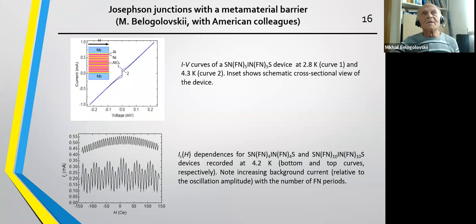But in several tens of these junctions, with aluminum oxide and without aluminum oxide, a Fraunhofer pattern was not observed. Rather, we saw a periodic structure, which is typical for SQUIDs. So we name it SQUID-like oscillations. Thus, for the first time in a Josephson junction made of simple metals, we could obtain such a periodic structure as the dependence of the critical current on the magnetic field. Sometimes it was such a strange curve with some beats.